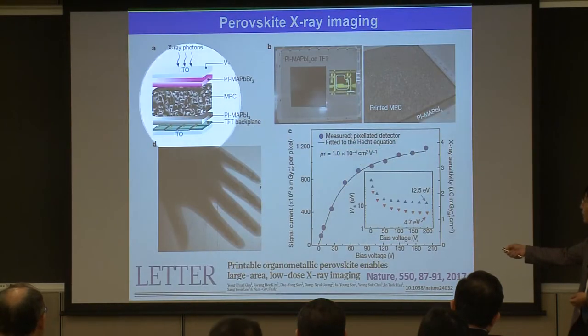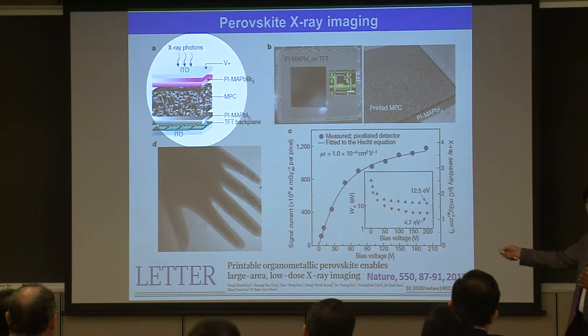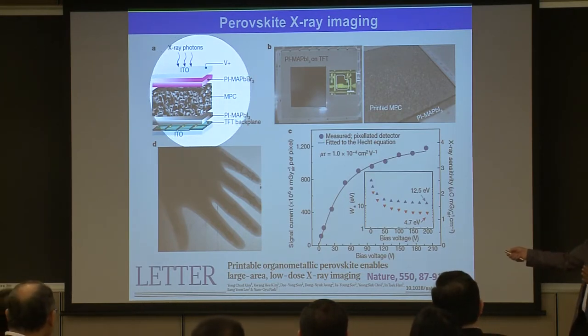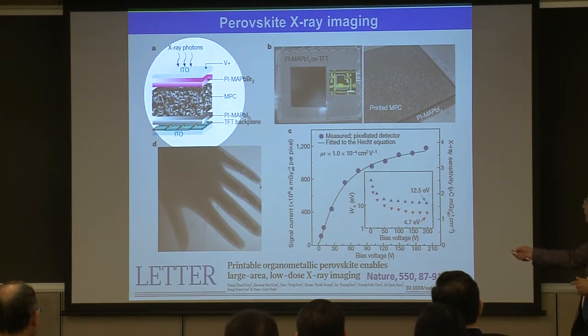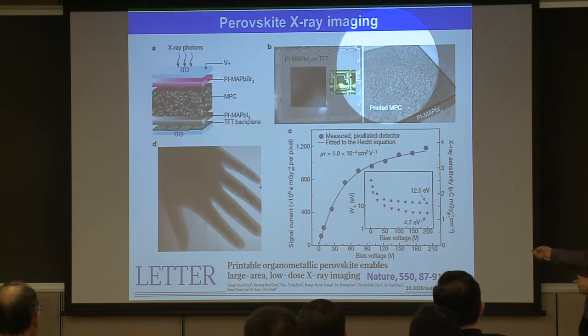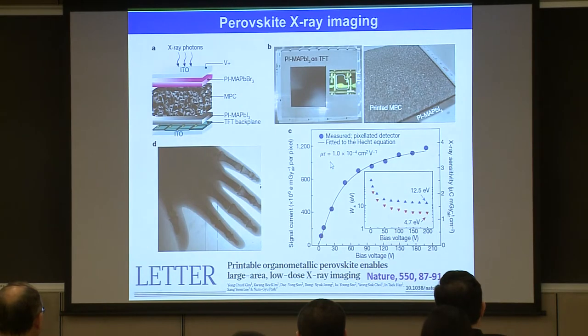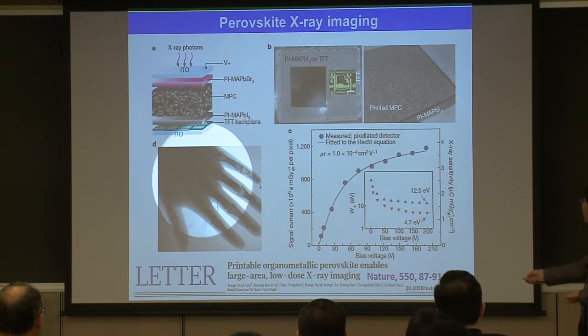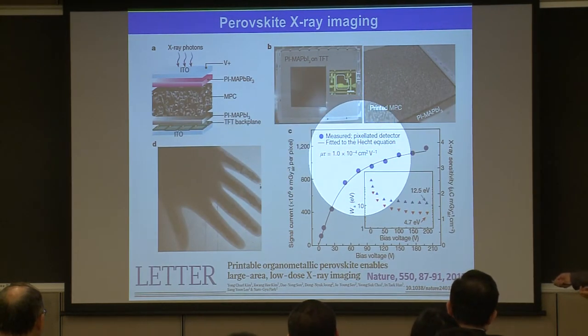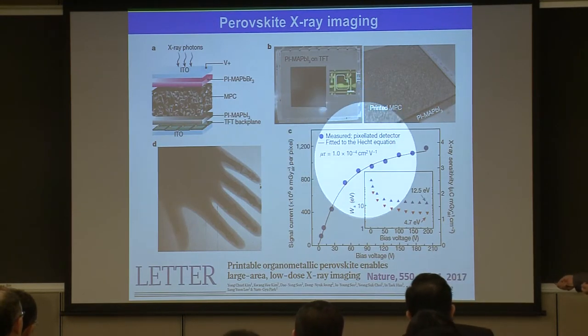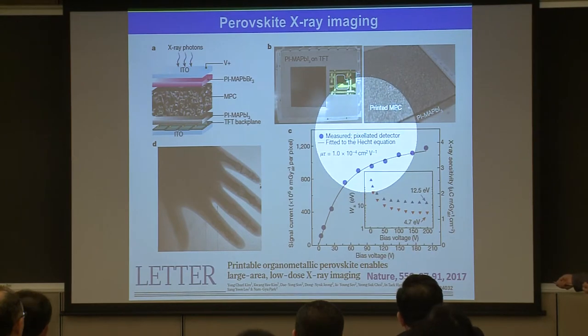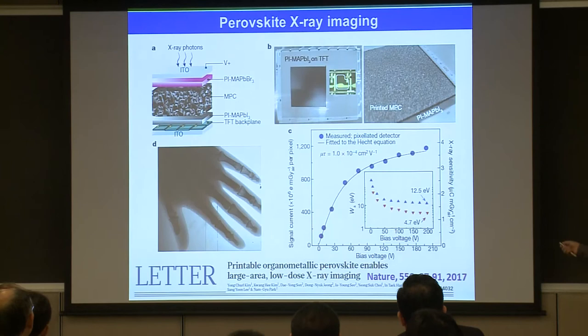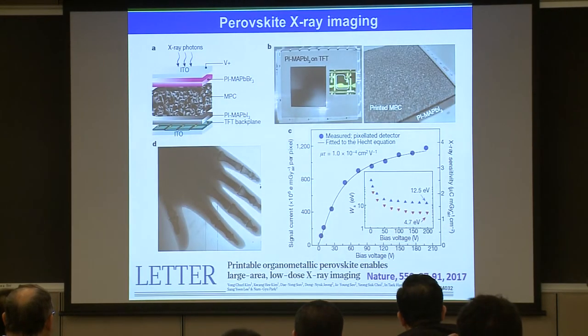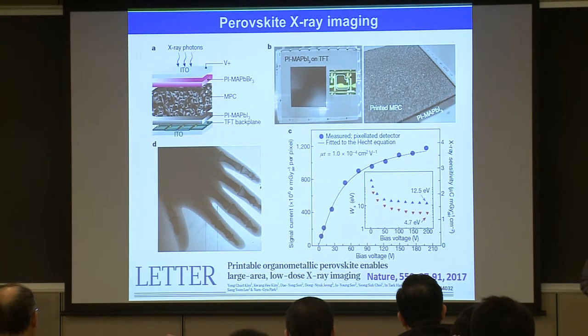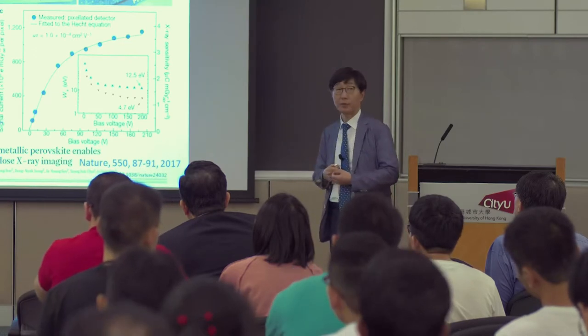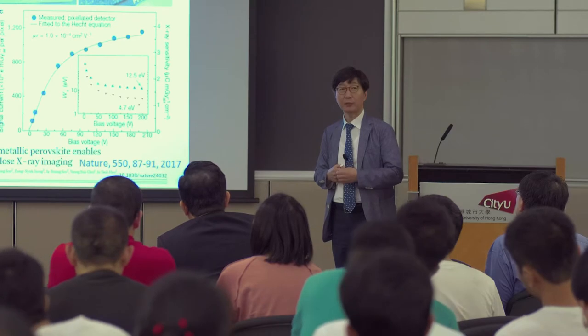And then we deposited this multicrystalline perovskite layer of about 800 micrometer on the TFT backplane. And this size is 10 by 10 centimeters. And then we measured a hand image. And from the time of flight measurement, the mu tau value, which is very important for the sensitivity, is about 10 to the minus 4 centimeter square per volt. This value is three orders of magnitude higher than amorphous selenium photo detector. So this material is a very promising material for X-ray imaging system.